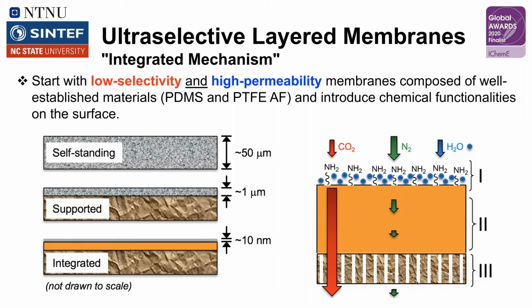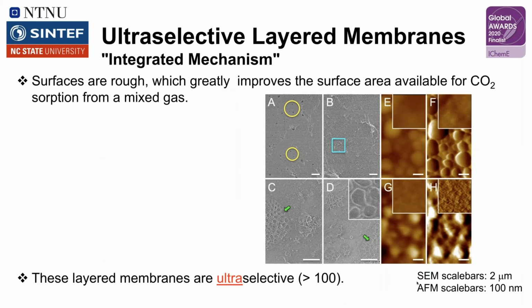So what we see within this range now is along the surface, we have species that are highly hydrophilic and they are highly CO2-philic. So amines, which you heard me mention earlier, are perfectly suited for this. Water stays within this range and allows us to take CO2 at one concentration and build that concentration level so that now when it goes through this high permeability zone, it's much more highly concentrated, and this is what we remove.